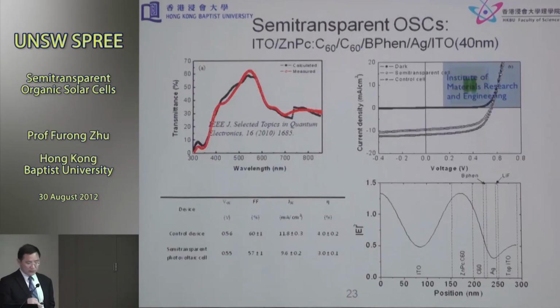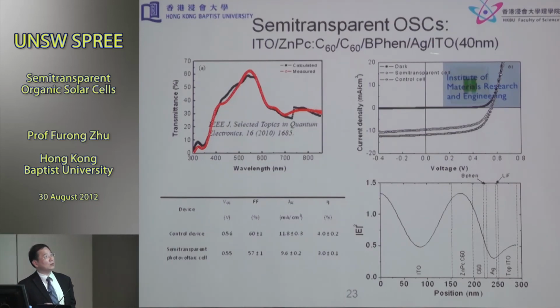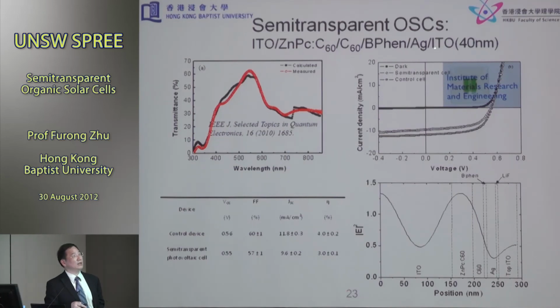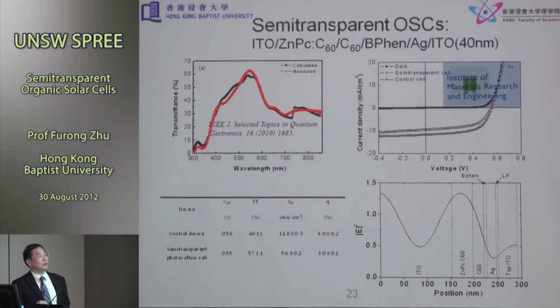So we expanded the work to include other systems. Essentially, the physics is the same, so we do the same design, and now we look into small molecule devices, zinc phthalocyanine (ZnPc) based. This is a sublimated device, made through thermal evaporation, and in this system we found that the common agreeable layer thickness for the top ITO, in terms of agreement between the absorbance and the transparency, is about 40 nanometers. The black curve is the simulated transmission of the entire device, and the red one is measured, because when you finish the device, you can always measure its transparency. They agree very well.